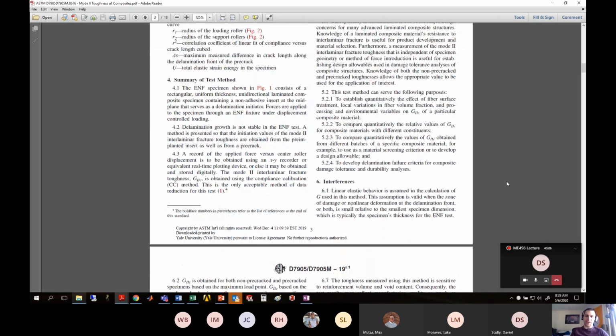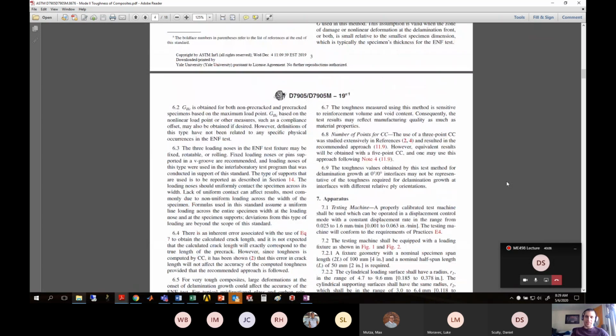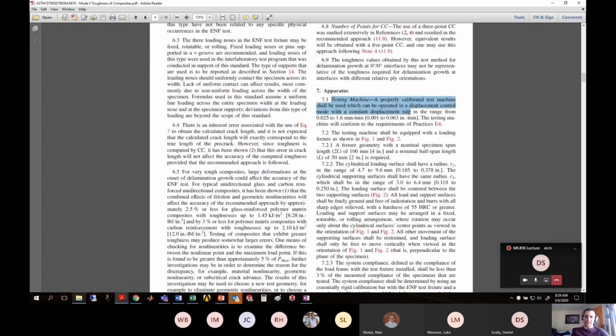Additional information on sample geometry. It talks about the apparatus that you need, what testing machine, displacement rates in the range of 0.025 to 1.6 millimeters per minute. So it goes into everything that you could possibly need. Talks about the specimen geometry, should have a span of 100 millimeters and a nominal half span of 50 millimeters, so on and so forth.